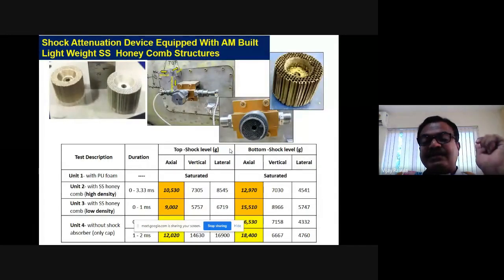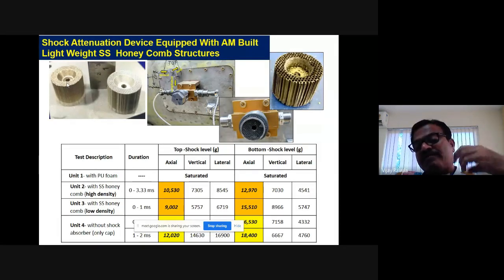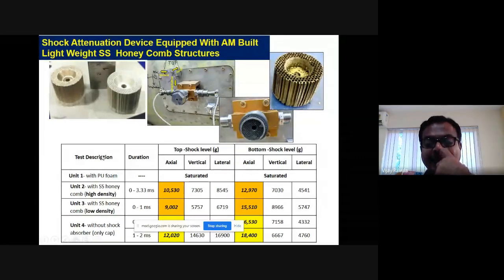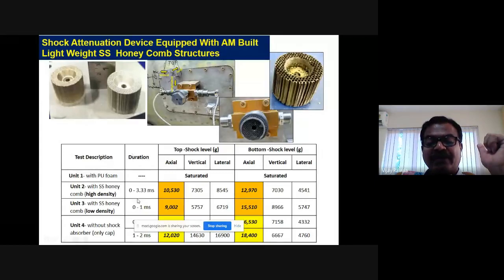And another thing is shock attenuators. It's like a honeycomb structure, for when there is a shock on the material. Earlier, people were using PU foam to absorb shock, but that was not working, so a metal honeycomb structure was proposed. That's what DRDL came to us for, and we could make stainless steel honeycomb structures. So you can see that.